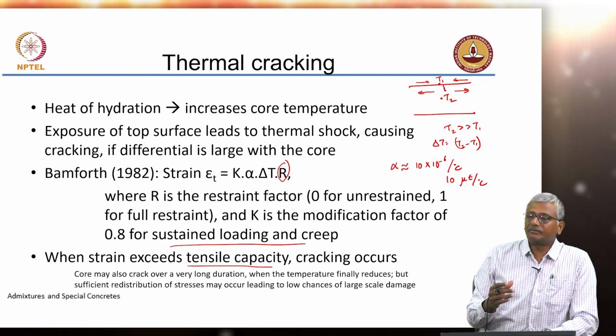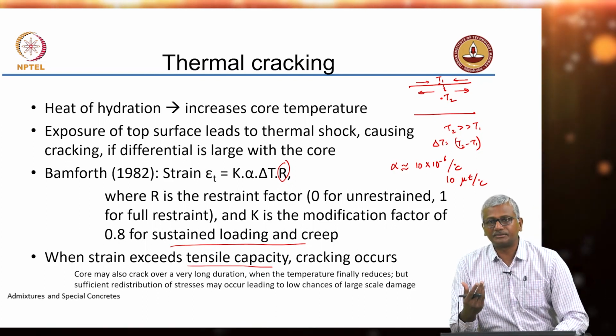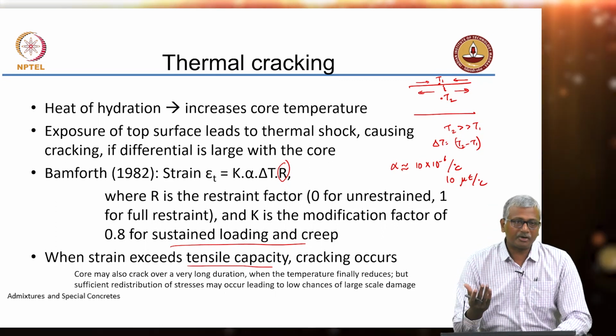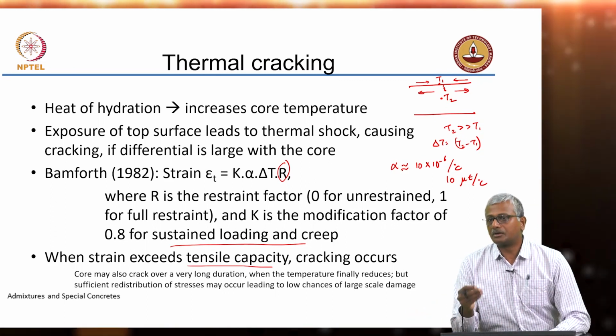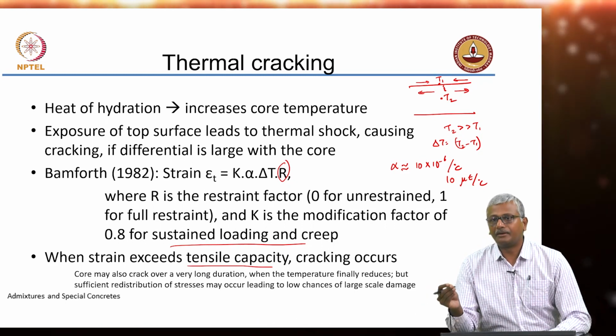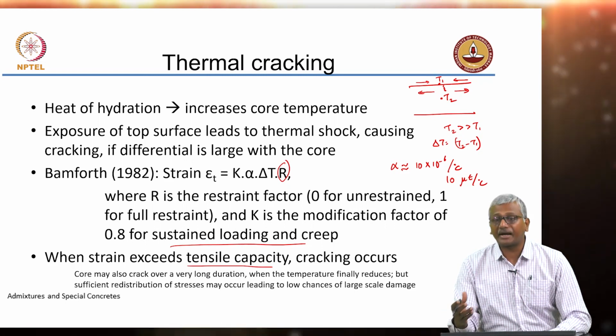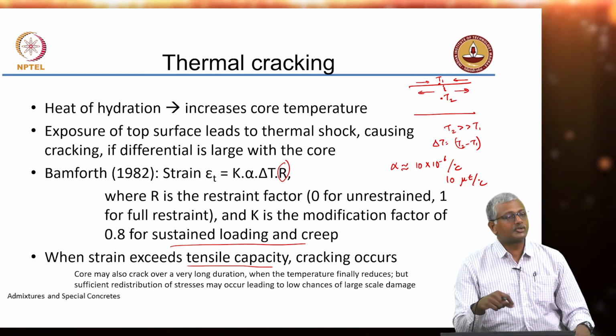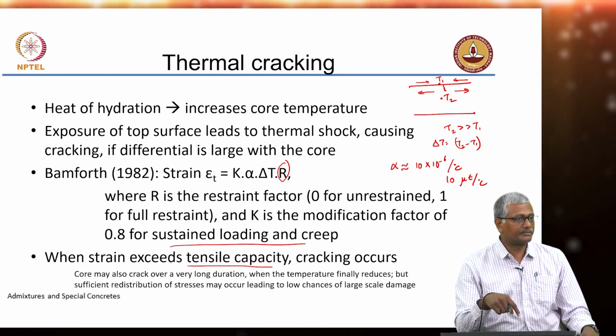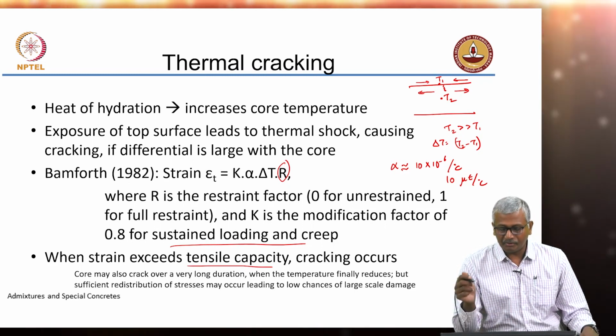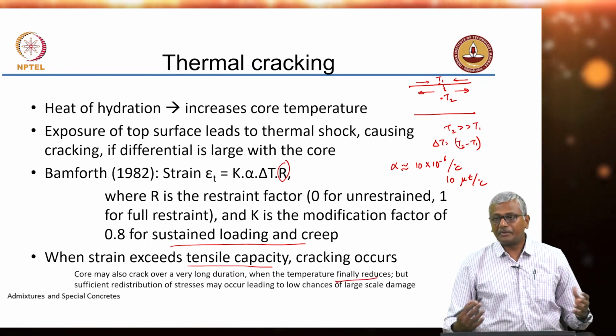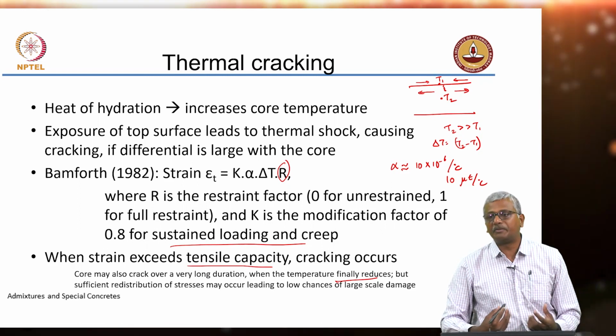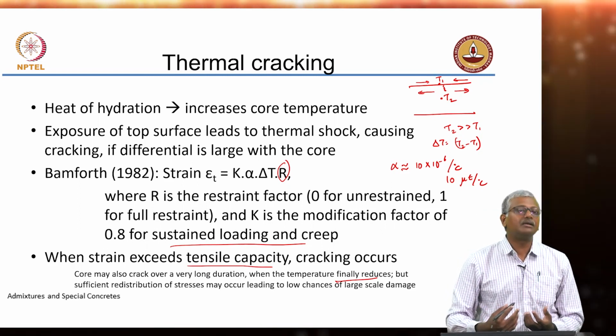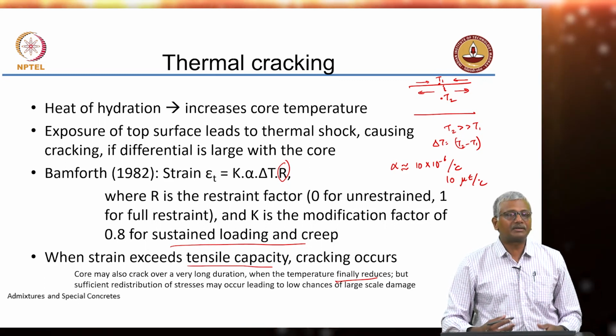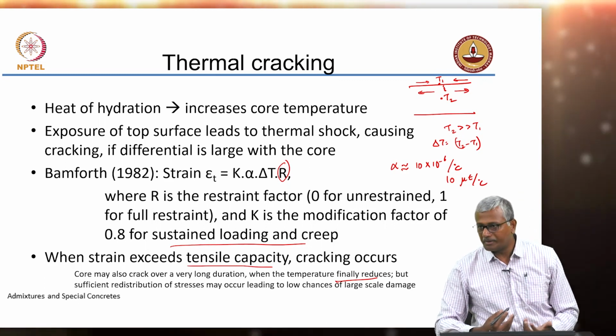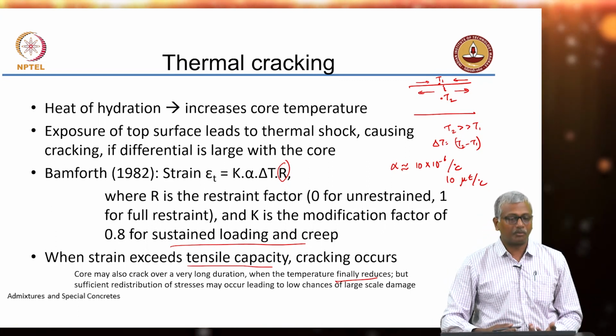Okay. However, you have to imagine that the core is not going to stay at that temperature. With time, maybe with long period of time, depending upon how massive your structure is, the core may tend to reduce its temperature, and the associated contraction of the concrete in the core may also lead to cracks in the core of the system, right. But that will happen over a very long period of time. When temperature finally reduces in the core, there will be contraction, and the movement because of that contraction, when it is resisted by the reinforcing steel, will obviously cause cracking. But because of the presence of the steel, the crack widths will be limited in the core, and it is not really going to be a debilitating problem for your system.